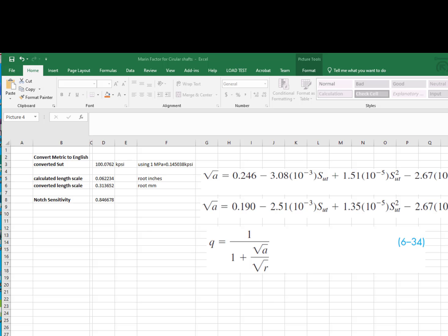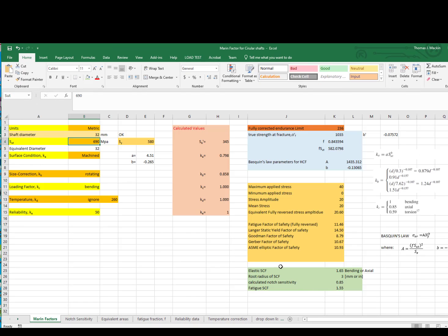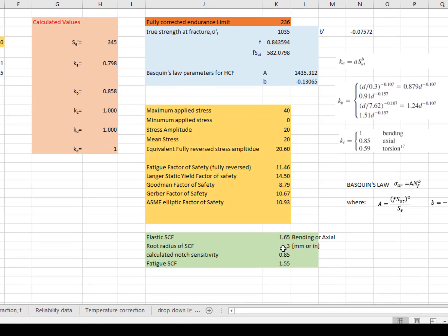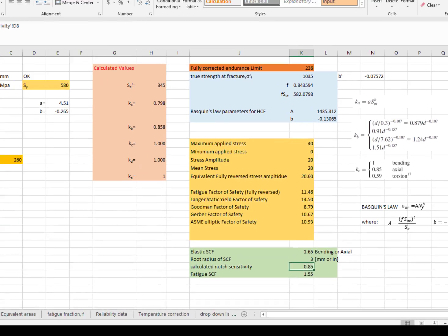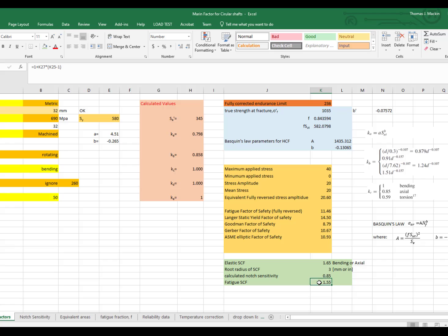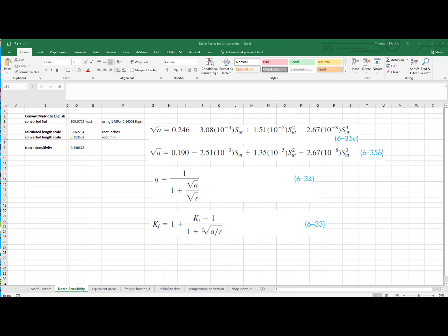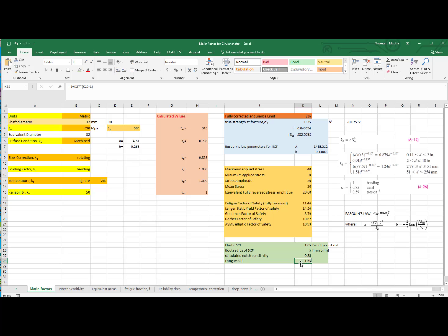Now I go back to my Marin factors worksheet and I see that my notch root radius was here in column K. I use this entry to calculate my Neuber length scale. I use this entry to calculate my notch sensitivity, which is shown here. There's my notch sensitivity, which I get from the other tab. And then I calculate the fatigue stress concentration factor. I calculate my fatigue stress concentration factor using equation 633, and that gets thrown into this cell right here.